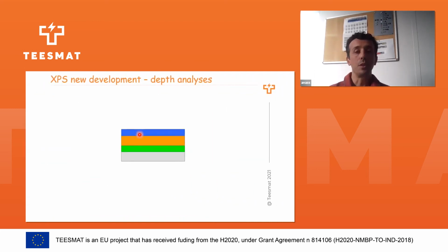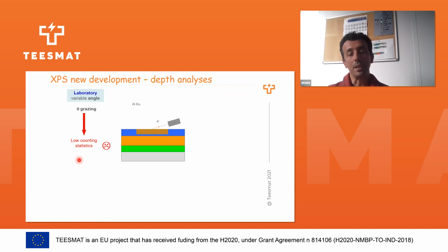And now I will come to the new development of XPS, like depth analysis. In XPS, we can do depth analysis in different ways. Either we can change the angle. That means we will change the angle of the photon through to the surface. The more we go to grazing angle, the more we probe the surface. But the problem in this case, when we probe the extreme surface, the count rate becomes low. So we need to acquire for a long time.